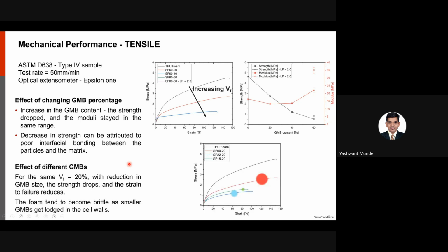Now, for the effect of different GMBs, we saw that as the GMB particle size reduced from bigger to smaller, the strength drops, and so does the strain to failure. That is, the foam tends to become more brittle as we go to smaller particles. But our main focus was compression, because of the high pressure conditions in underwater vehicles and things like that. So we wanted to understand the performance under compression.